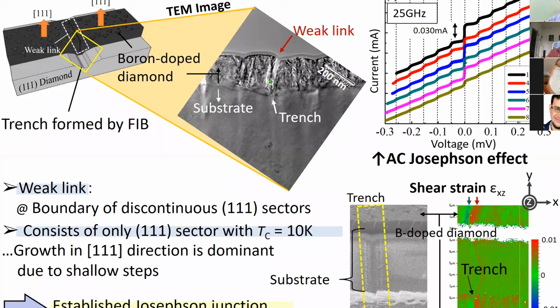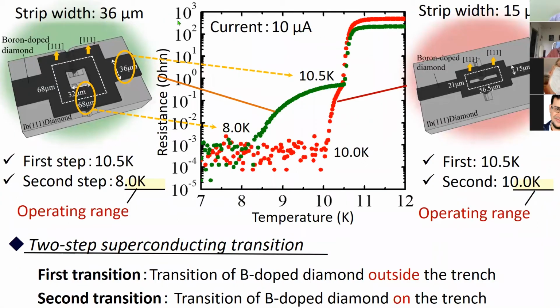One of the most important things is the IV characteristic - the resistance and temperature relationship. We have a two-phase behavior: two-phase meaning a TC of 10 Kelvin regions and relatively low temperature regions. In this case, it's 8 Kelvin, for example. So the two-step transition takes place, which is evidence for the Josephson junctions.